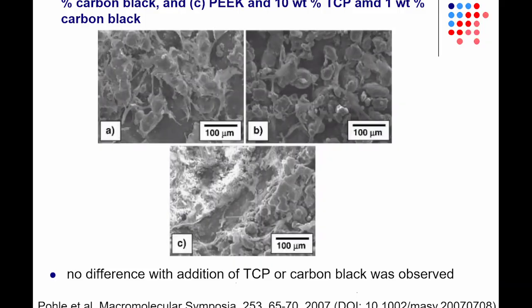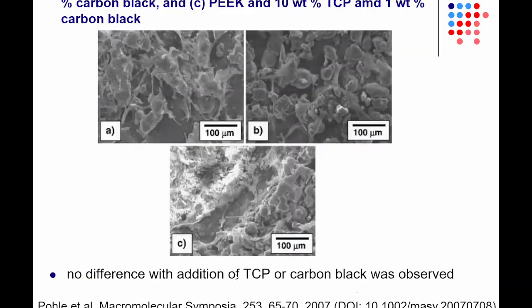Although it should be noted that PEEK itself is somewhat hydrophobic, and you have the advantage of being able to add tricalcium phosphate to enhance cell attachment. But you can see there's really no difference here whether tricalcium phosphate or carbon black was added. Getting good cell growth on any of these, even though you would think on first principles adding calcium and phosphorus on the material surface would enhance osteoblast attachment and growth. You can see here the actual research result shows no difference with the addition of tricalcium phosphate or carbon black.